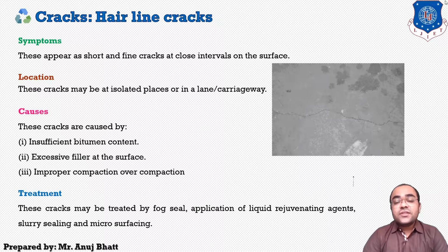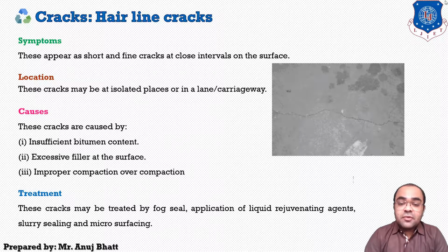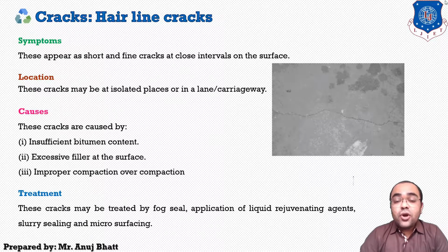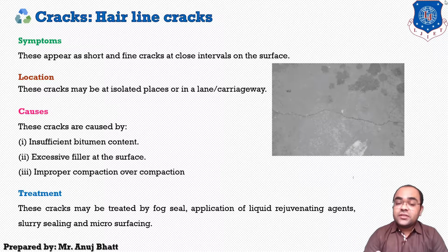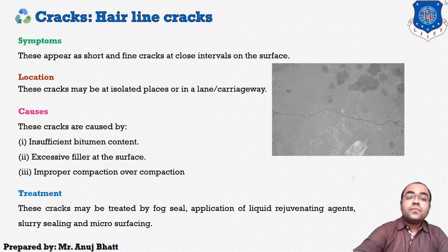The causes of such cracks are insufficient bitumen content, maybe excessive filler in the surface layer, or improper compaction. If the compaction is done in an excessive manner, it will also cause cracks.